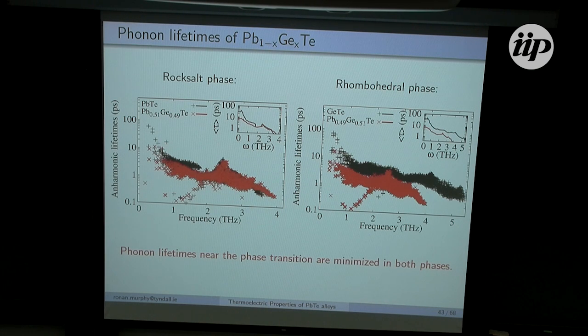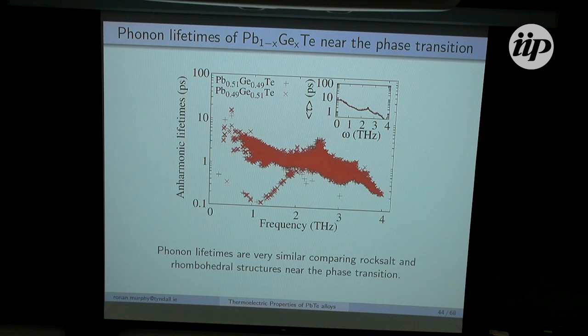And just to focus a bit more on that particular point, here's a plot of the phonon lifetimes of the rock salt alloy on the verge of the phase transition in black, and then in red, the rhombohedral alloy on the verge of the phase transition. And you see that they're actually remarkably similar. It's very difficult to even tell them apart. And again, if you look here at the average phonon lifetimes, it's a similar story. So this just points out two things. The first one being that our phonon lifetimes are minimized at the phase transition, but also in these lead germanium telluride alloys, they undergo a second order phase transition. So properties such as the phonon lifetimes and lattice parameters should vary continuously.